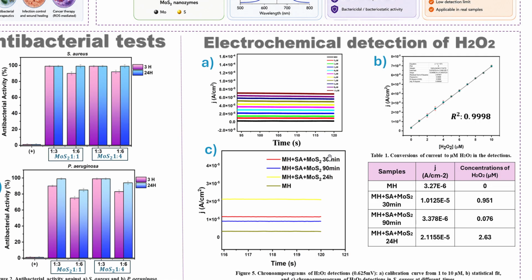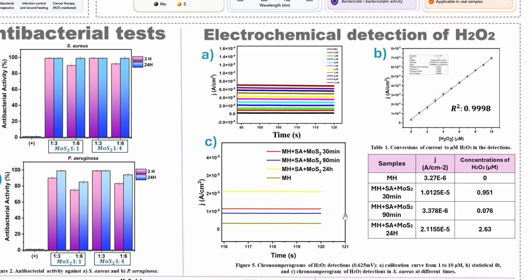We then applied this electrochemical approach to the bacterial samples exposed to molybdenum disulfide. Changes in the electrochemical response were observed depending on the incubation condition and exposure time. This demonstrates the potential of electrochemical techniques as complementary tools for investigating hydrogen peroxide-related processes present in biological systems.